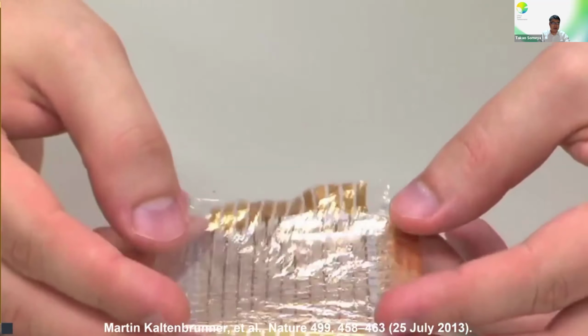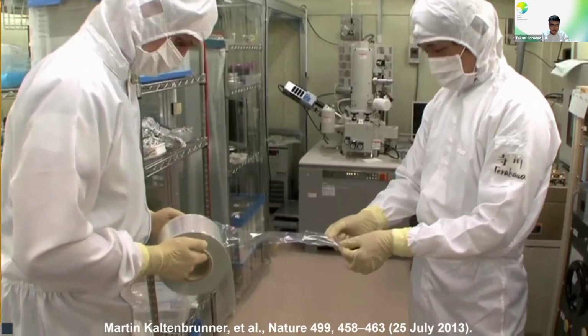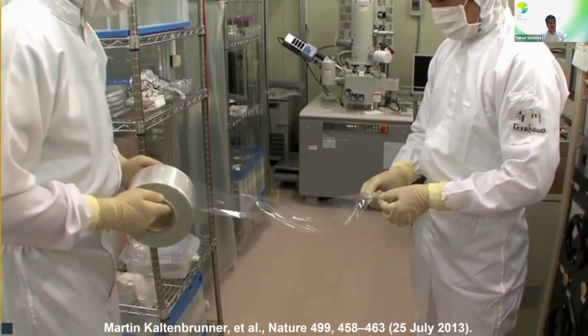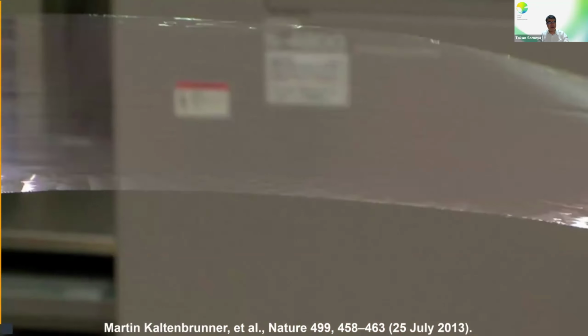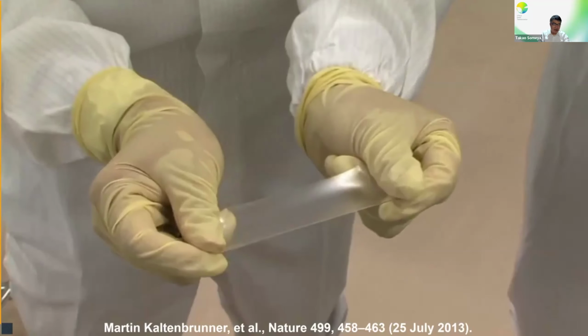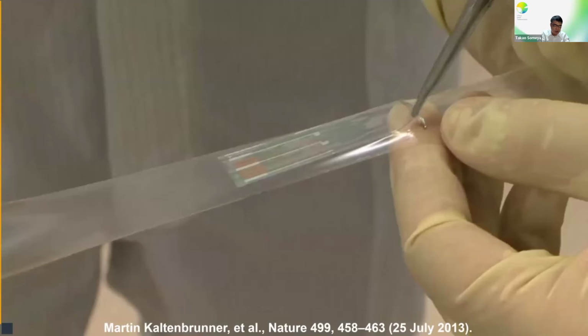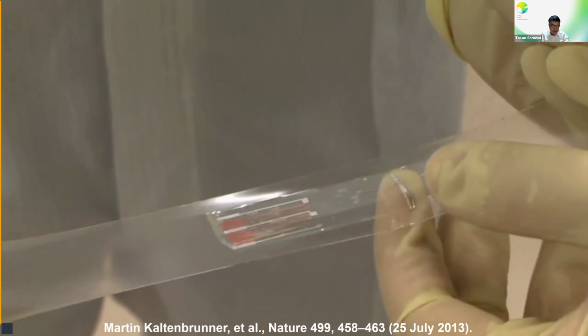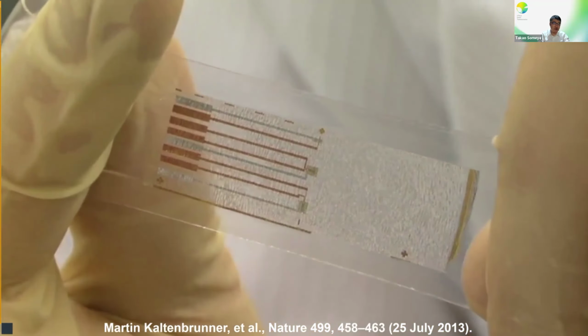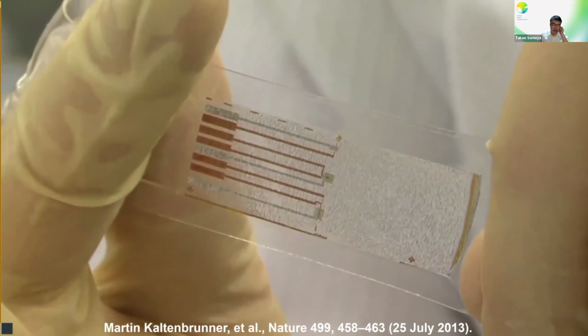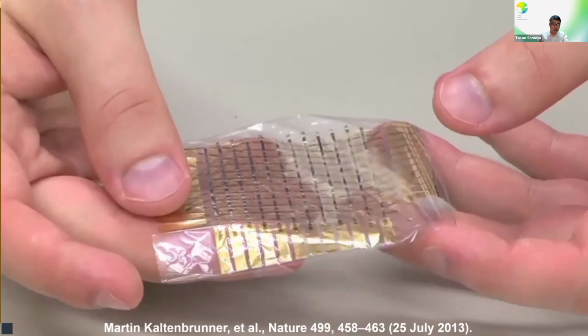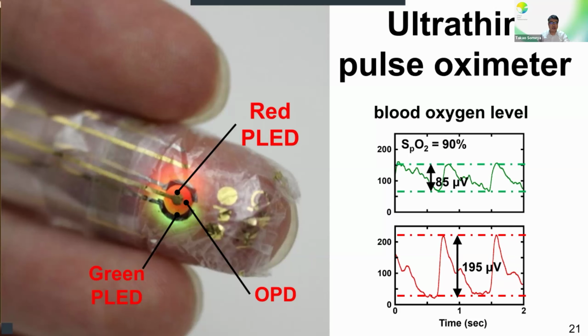So we utilize the 1 micron thick PET film, commercially available with reasonable price. And after fabrication, we prepare the pre-stretching rubber, laminated together, and transform the surface into a wrinkling structure, like an accordion structure. In that way, ultra-thin film devices could be transformed into stretchable devices very easily.